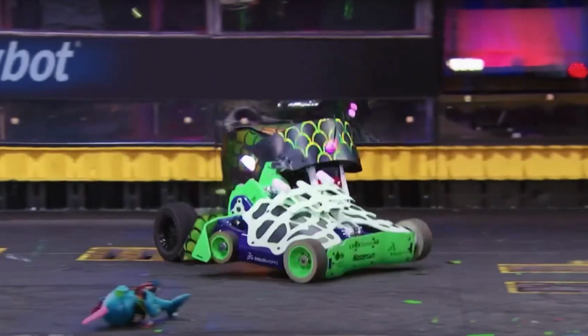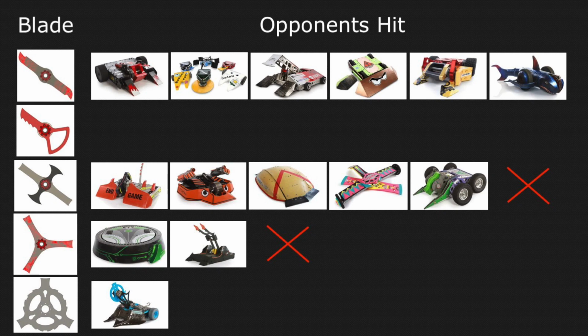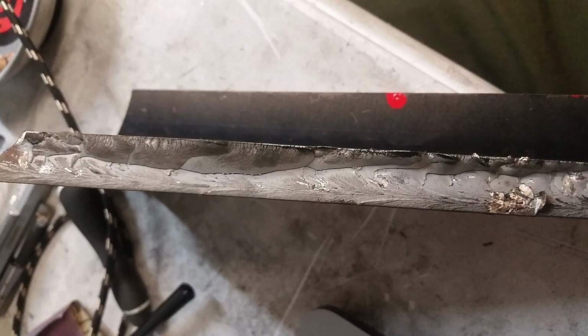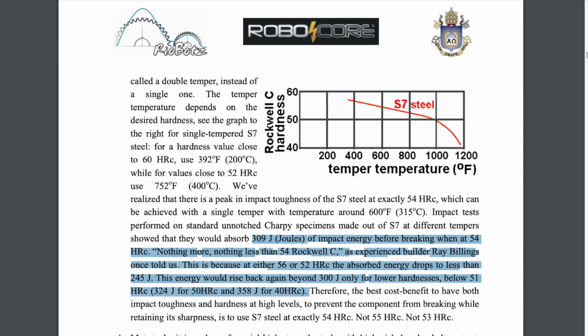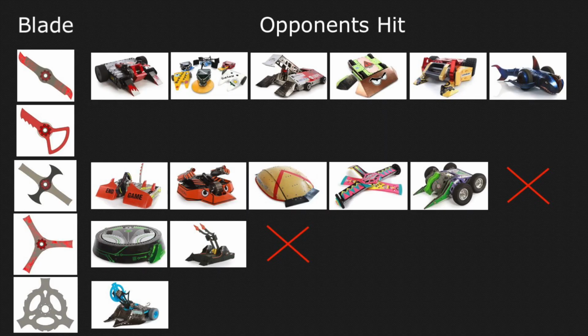Material issues have been known to happen with weapons like these, like what happened to Witch Doctor this year. The fact that our 2019 blade survived while our 2020 batch didn't makes it tempting to blame bad material or heat treatment. However, we hardness tested the pieces after filming was over, and they were at exactly the 54 Rockwell C hardness that we asked for, which according to the data in the RoboCore manual is the best temper to use for an S7 weapon. Our blades also survived a lot longer than the ones that the Witch Doctor team said were defective, so we don't think that's the culprit in our case.